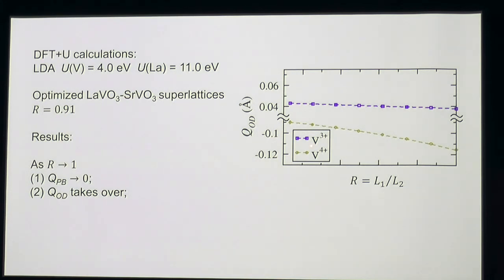We can see that as R goes toward 1, the off-centering displacement of vanadium 4+ keeps increasing, which means if we artificially take away the polyhedral breathing character, the other effect, the off-centering effect, will take over and become dominant.